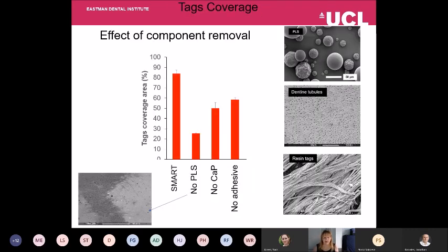What this has done is helped us to optimize the formulation, to come up with a formulation that seals practically the whole surface of any dentine tubules. What these results here show is if we take that optimized formulation and take out our polylysine, our coverage goes down from around 85% down to just 25%. Polylysine is the most important.